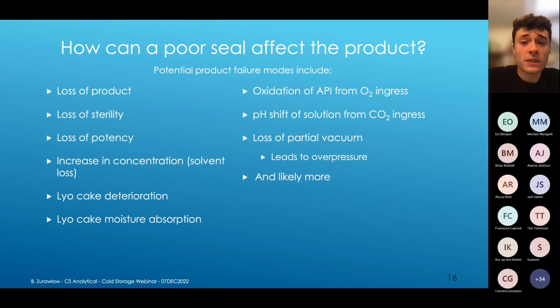So if there is in fact a poor seal present, how can that go about affecting the product? So of course, as we talked about in the maximum allowable leakage limit example, we can literally lose the product from the package system, which is inherently an issue. We could have a loss of sterility, a loss of potency, an increase in concentration of API as a result of solvent loss. In the case of lyo products, we can have cake collapse, deterioration, and moisture absorption. In the case of headspace or gas-sensitive products, we can have an oxidation of API if oxygen gets in that package, a pH shift of a liquid solution if CO2 enters that package and then dissolves into solution. We could have a partial loss of vacuum leading to overpressure upon reconstitution, and likely many more potential failure modes associated with a poor seal.